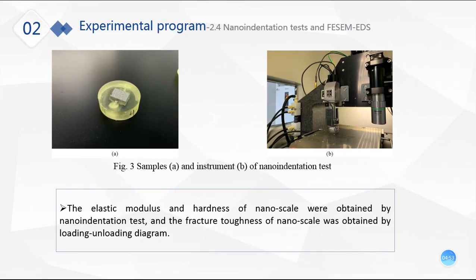The elastic modulus and hardness at nanoscale were obtained by nano indentation test, and the fracture toughness at nanoscale was obtained by the loading-unloading diagram. This is the sample for the nano indentation test, and the right one is the instrument, the machine for nano indentation test.